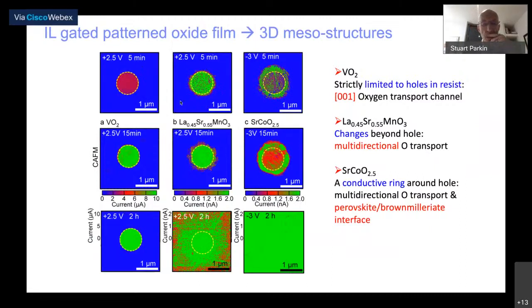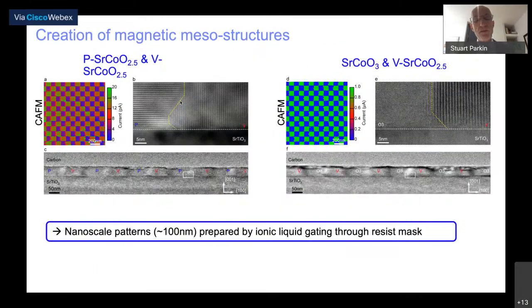Without going into details, as I'm running out of time, we can now form very complex spin textures, shown on the left in this checkerboard image. This is the conducting atomic force microscope image of a film of strontium cobalt oxide, where we've converted the purple regions to a form of the brownmillerite where the oxygen vacancy layers are horizontal, and neighboring regions are vertical. You can see the boundary between these regions is just 5 nanometers wide. Underneath is a transmission electron microscopy image, in conventional imaging mode, where we go from a parallel to a vertical orientation of these regions on a scale of approximately 100 nanometers.